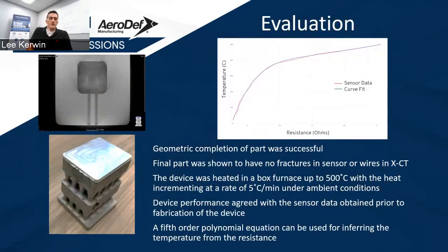So we evaluated the final part after we encapsulated the sensor, one by doing X-ray CT on it. In a couple of the earlier attempts, we did see cracking in the sensor after encapsulation. So in this final one, with the final setup of the slot depth and how we were fixing that sensor in the channel, we saw no fractures in the sensor or the wires that were coming out in that X-ray CT scan.